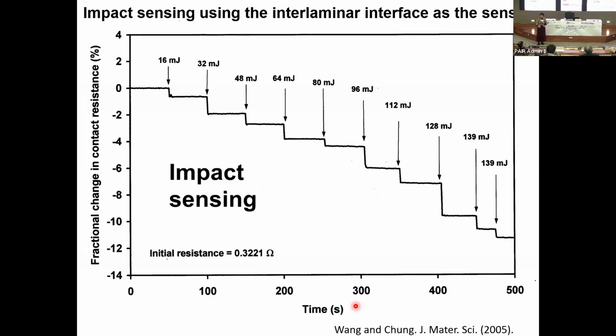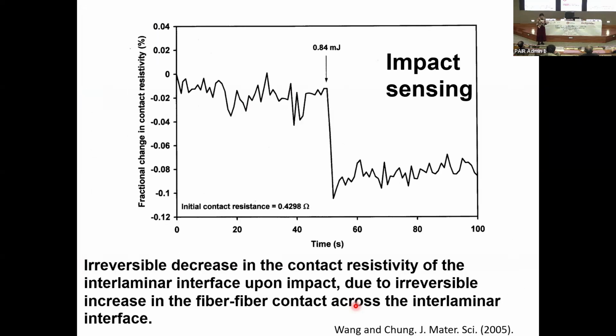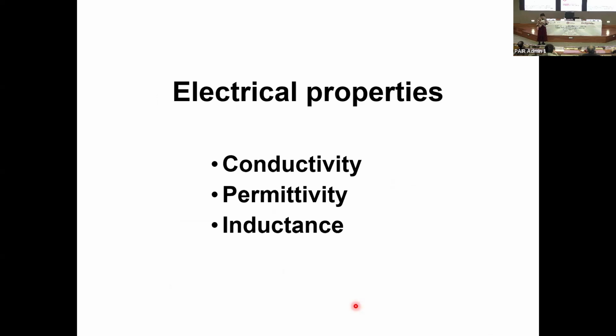The contact resistance of the interlaminar interface decreases irreversibly upon impact at progressively increasing impact energy in millijoules. Okay? Every time one impacts, the contact resistance decreases irreversibly. And even at a tiny impact energy of 0.8 millijoules, we can detect it. So sensitive. And this irreversible decrease in the contact resistivity of the interface upon impact is due to the irreversible increase in the fiber-fiber contact across the interlaminar interface.